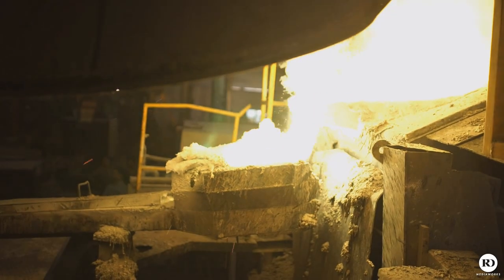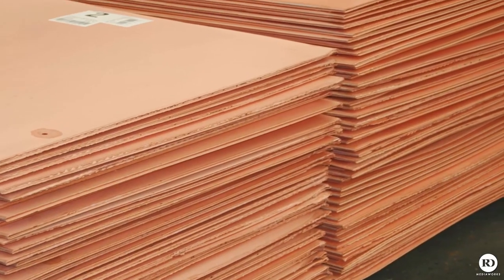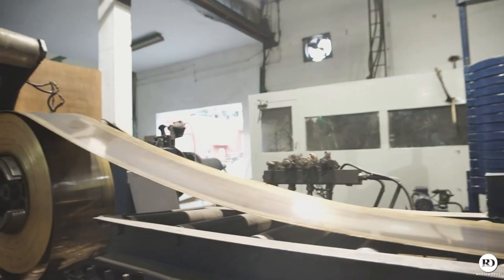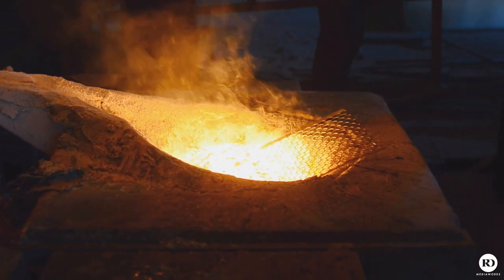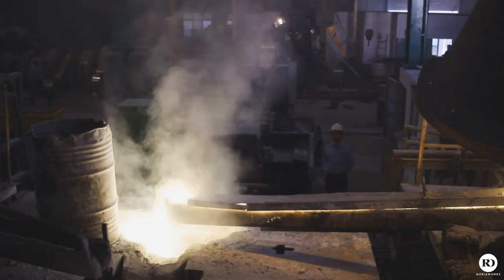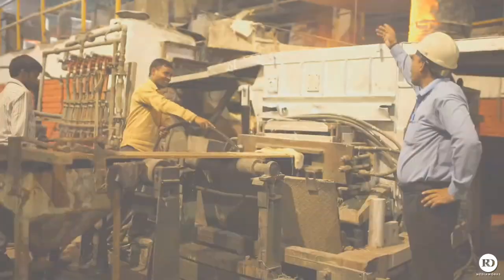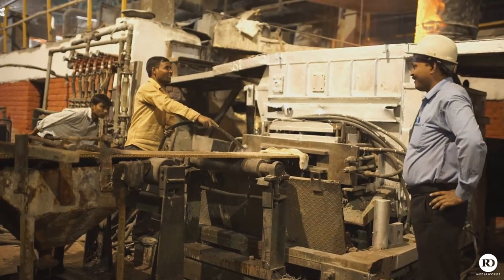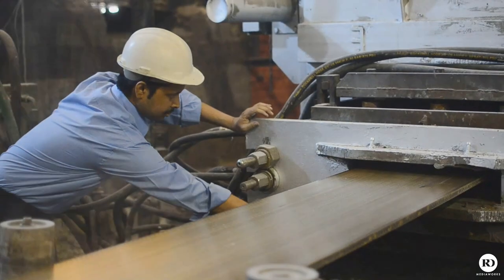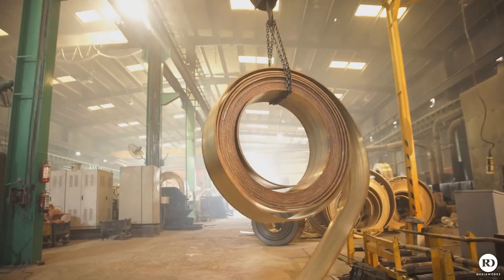The production process of coin blanks starts at the melt shop, where the alloy combination is made. We are using high-quality copper, nickel, zinc and aluminium, which are procured from reliable and established international suppliers. The production begins with the molten metal being cast into coils 450 mm width and 16.5 mm thickness by horizontal continuous cast process. During the casting process, there is a layer of oxidation that is found on the strips, and these strips are milled on both sides to approximately 0.8 mm on each side, which removes the oxidation and makes the strip ready for the cold rolling process.